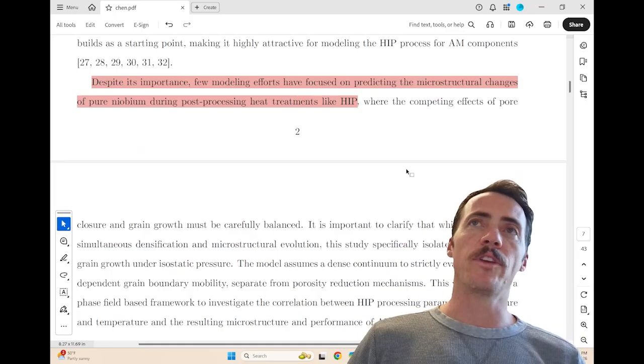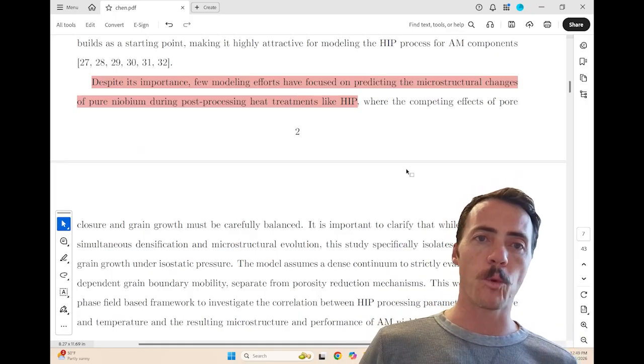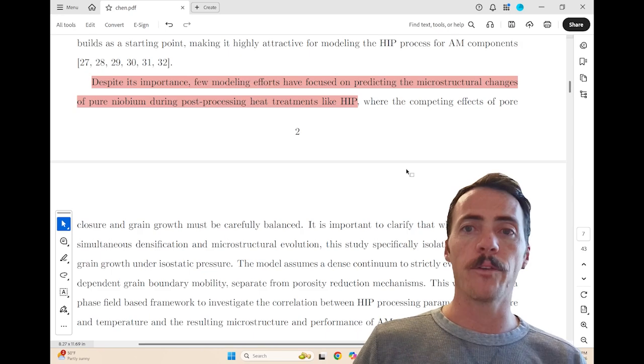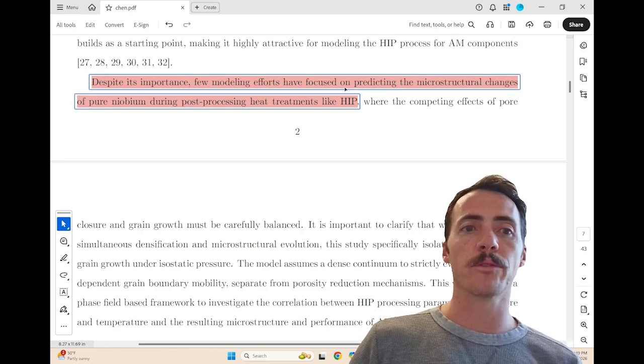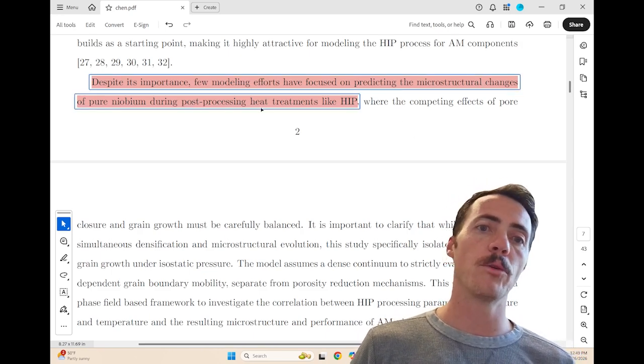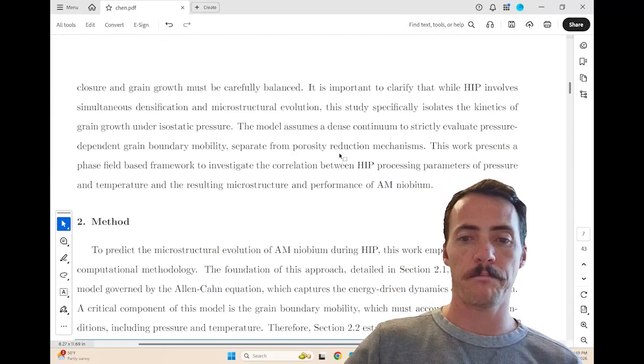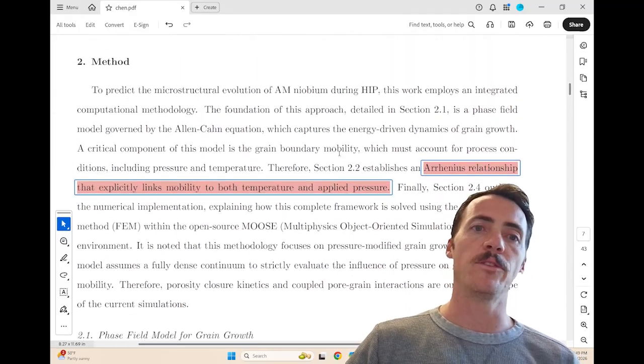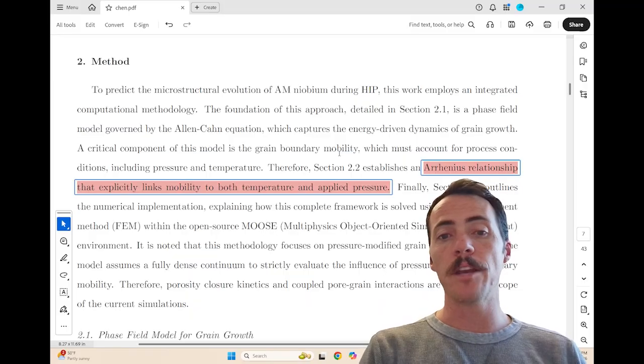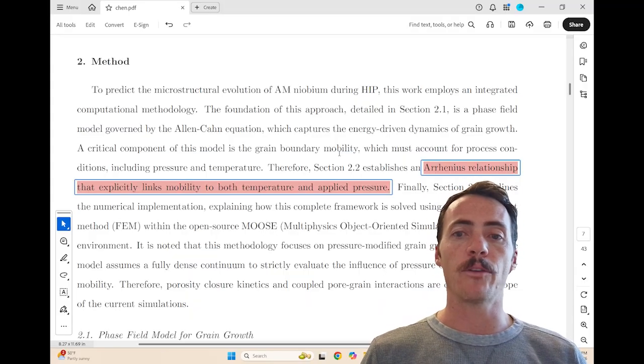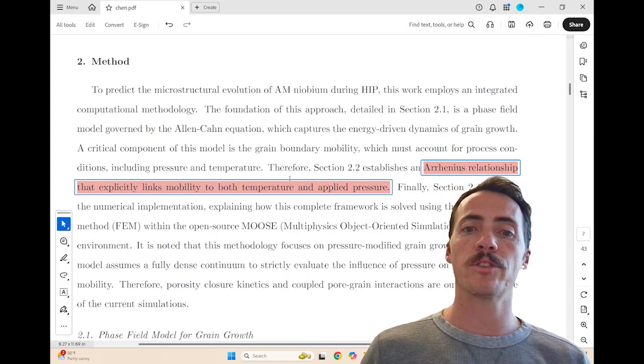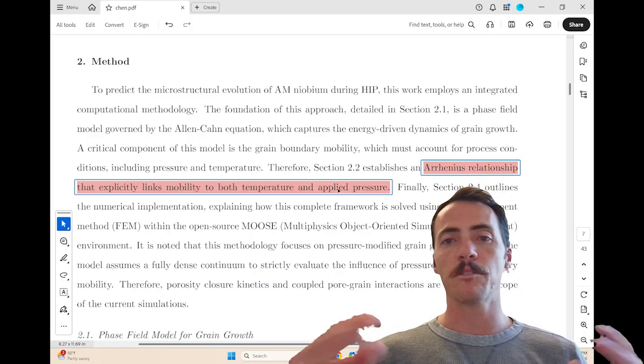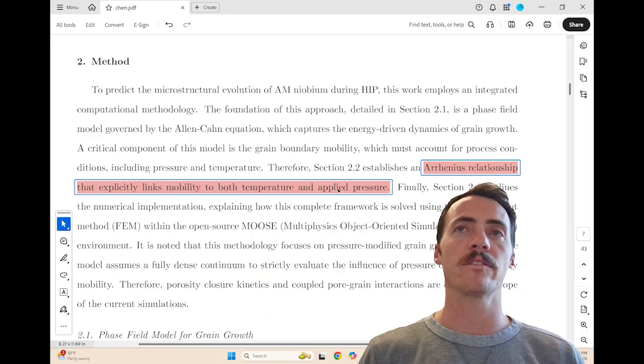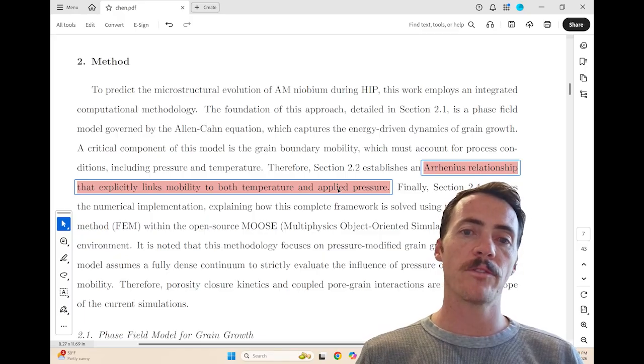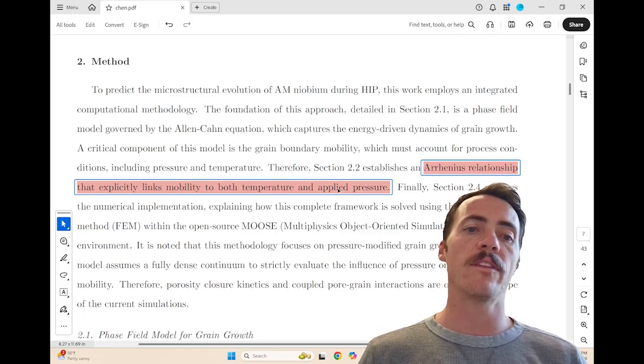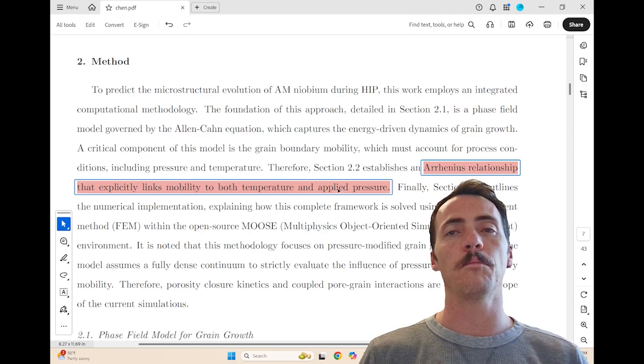So that's exactly what the authors are going to try and introduce, is a framework whereby you can, through modeling efforts, try and actually predict these microstructural changes for pure niobium during post-processing heat treatments like hipping. All right, so one of the cool things that they do here is they're actually going to treat the grain mobility as an Arrhenius relationship, linking it to both temperature and pressure. Instead of doing a sort of design of experiment or randomly exploring different things, they're actually trying to learn these parameters from the Arrhenius equation so that they can then integrate those into their modeling framework.